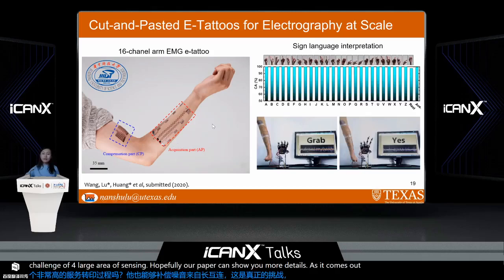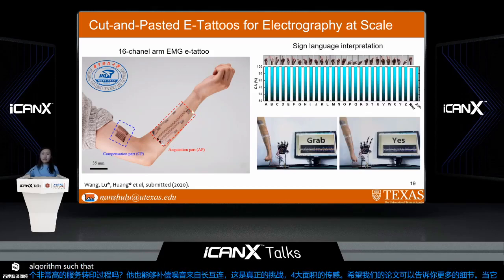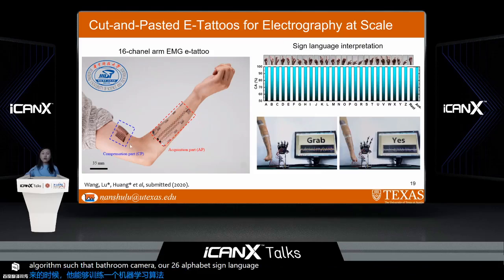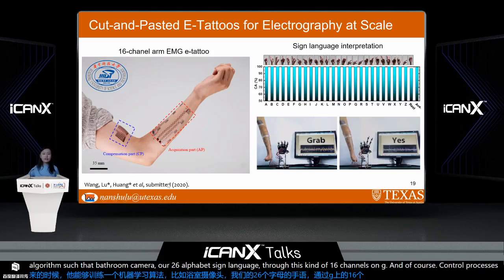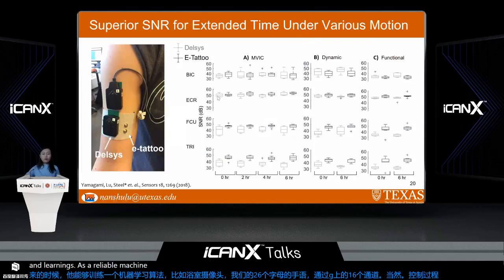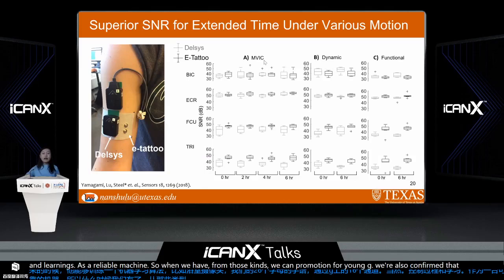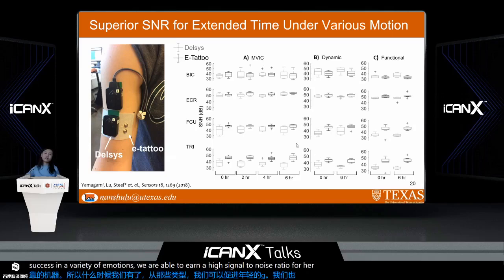And he was able to train a machine learning algorithm such that it can recognize our 26-alphabet sign language through this kind of 16-channel arm EMG. And of course, we can control processes and many other things as a reliable human machine interface. When we have those kinds of mechanical motion for EMG, we also confirmed that under long term, up to 6 hours, and under a variety of motion, we are able to maintain the high signal to noise ratio for e-tattoos compared with conventional rigid box Delsys EMG systems. And this is, again, thanks to this robust interface between the two.